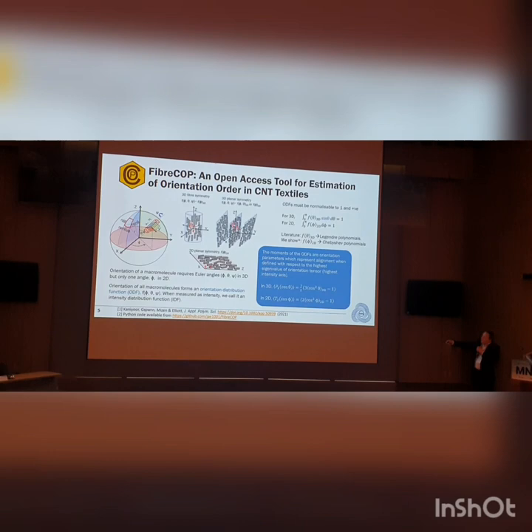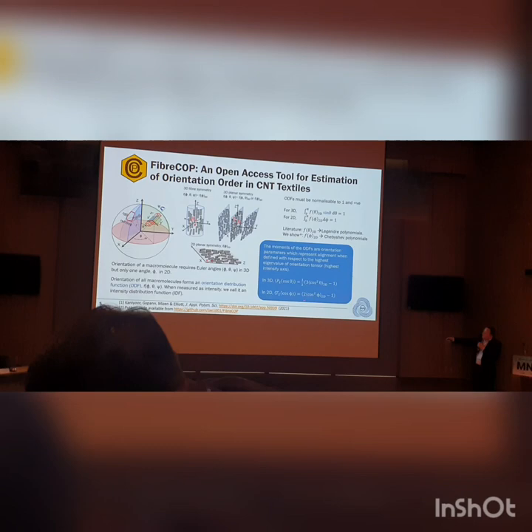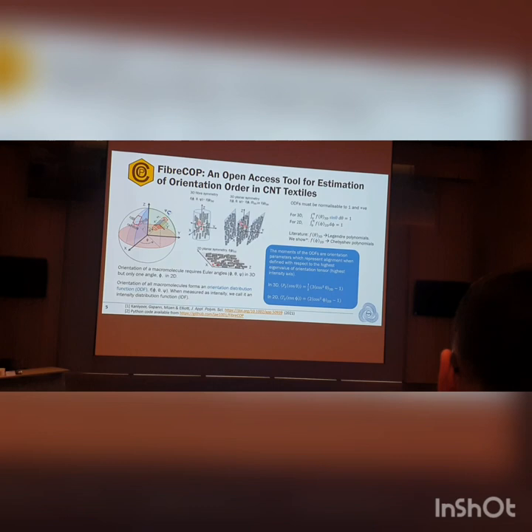The orientation distributions in 2D and 3D have different normalization constants because angles behave differently in two versus three dimensions. In this talk I'm mostly using the t2 alignment parameter — a function of the cosine of the angle, which is the lowest even-order moment of the orientation distribution in two dimensions. This is slightly different from p2, which measures the lowest even-order moment in three dimensions. If you calculate one for the wrong dimensionality, your alignment measure can be wrong by as much as 80%. We also have a Python script called FibreCOP which calculates these orientation parameters from 2D and 3D data.